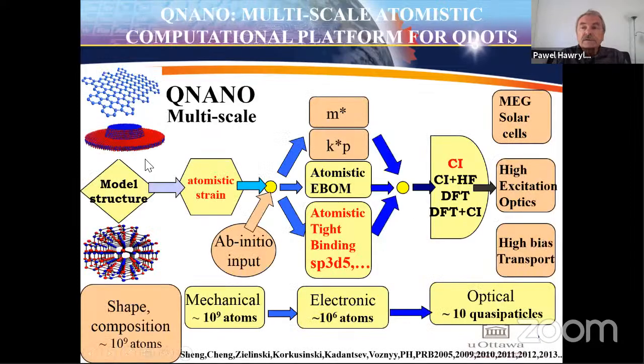So QNano consists of several steps. The first step is we define the structure. So we define the shape, the composition of atoms, where each and every atom is. So for example, we start with indium and arsenide atoms in positions of gallium arsenide. Then we calculate atomistic strain. So we calculate total elastic energy and determine where these atoms really are.